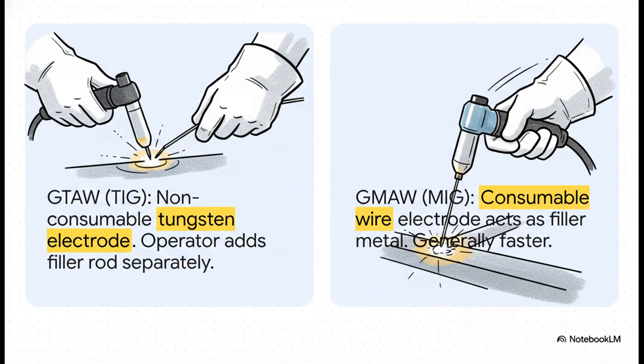Okay, so the biggest difference really boils down to this. With TIG, you've got a tungsten electrode that doesn't melt, and you use your other hand to carefully feed in a filler rod. It's a two-handed operation, which gives you incredible pinpoint control. Now with MIG, the wire you're feeding is both the electrode and the filler metal all in one. It shoots out of the gun continuously. It's way faster, but that speed comes with some trade-offs.